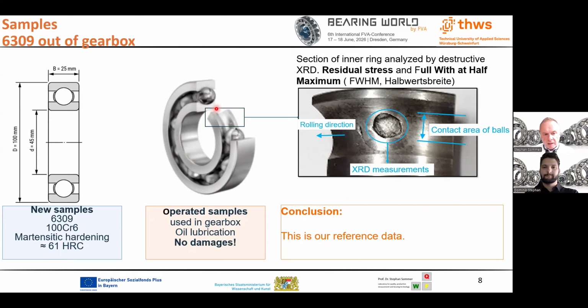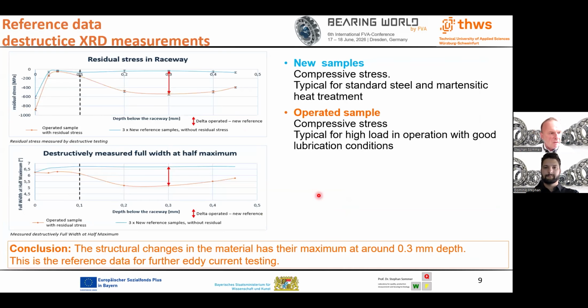So what we do, we cut out a section here, and in this section of the ring, we are measuring right in the middle of the contact area of the balls. We measure the X-ray diffraction. This is this hole here, right in the middle of the contact area in rolling direction. So the conclusion is, this is our reference data. Now, how does this reference data look like?